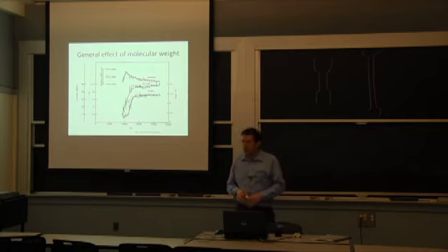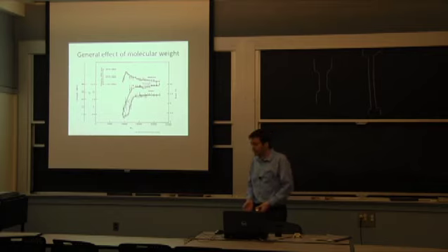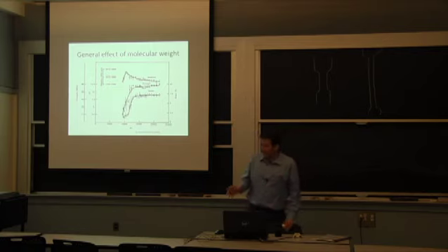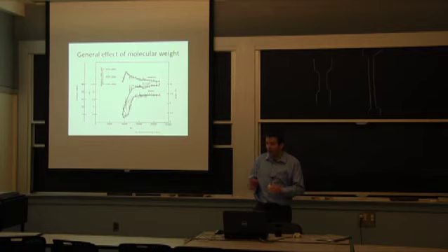Yeah, you put more weight into it. You have to be careful about what you're looking at, because when you accelerate a test, you can get a failure mechanism that's different. So it's okay to accelerate viscoelasticity, because viscoelasticity is moving things around. And the best way to do it is actually to increase the temperature. When you do that, you don't get the same risk of forming crazes, for example, because that's temperature dependent. So it only helps you better predict the viscoelastic response. And that's my personal view of what people do. Most of the time, they manage to accelerate it a lot by going to a higher temperature.